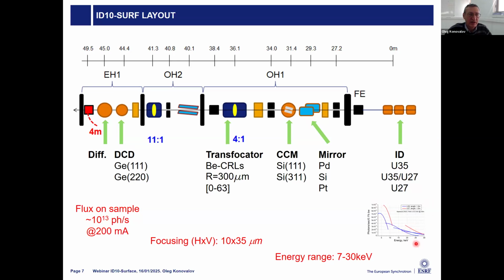And here is the spectrum which these undulators give. Red is U27 and blue is U35. From here, you can see immediately why we need U35. It just covers the gap we have for the U27 undulator. But U27 gives much more intensity. If some experiments need less intensity, but especially the beam within the range in this gap, then we can apply the U35 undulators. Afterwards, we have a horizontally oriented mirror with different coatings, palladium, silicon, platinum. This is to work at different energies. And then we have a monochromator with a channel-cut crystal.